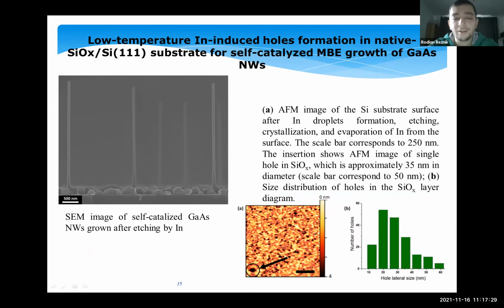Answering your last question, the density of the holes and nanowires is the same. So, and as I remember, maybe now I'm not correct, but this is something about the temperature of growth of gallium arsenide, so about 500 degrees. So using this temperature, we can evaporate indium from the substrate. Okay, very nice. Thank you.